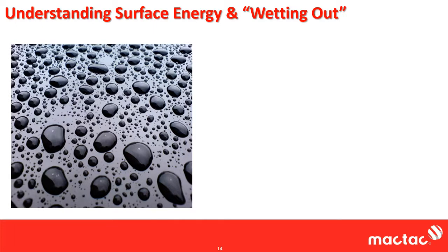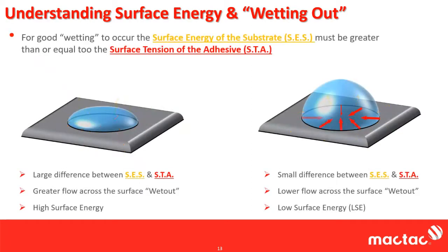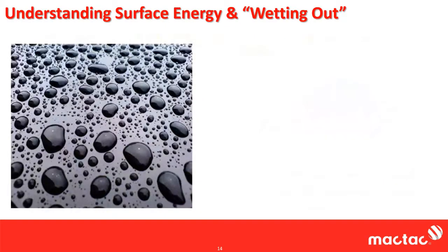But if you ever notice that after you wax your car and it gets wet, you get a lot of beads forming up. Well, the reason for that is that water is a very high surface tension material, and wax is a very low surface energy surface. And so you get the example on the right. When you have something that has high surface tension on a surface that has very low surface energy, you get a very highly formed distinct bead. When the car isn't waxed, sometimes you can't even tell it's wet because the water just wets all the way across, say, the hood, and you can't even see distinct beads. That's because the paint or the clear coat used on the car is very high surface energy, and the water wets across that as compared to the wax.